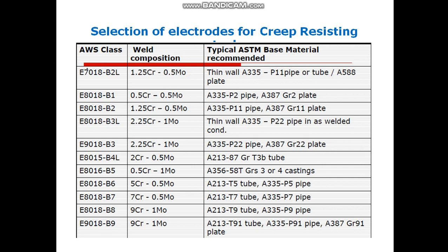This table gives some selection of electrodes for creep resisting steel. Now the American Welding Society classified electrodes for different weld compositions, 1 quarter chrome half moly to 9 chrome 1 moly, suitable for typical ASTM base material. They are recommended for ASTM A335 pipe material P11, for A213 tube material, for A335, and for A387 grade 91 plate material.